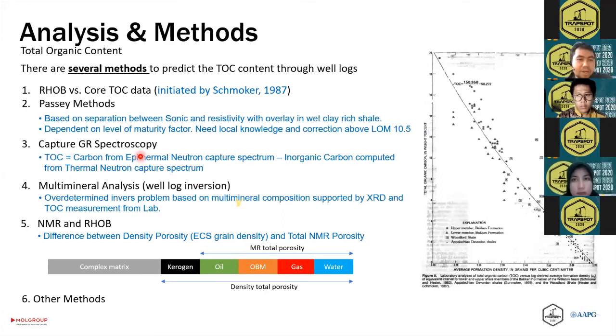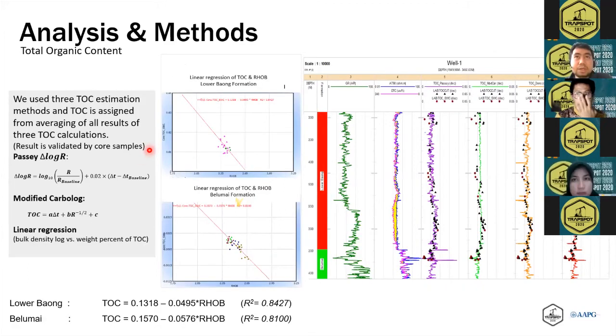What I did to calculate the TOC, you can see here: I have the TOC calculated from the Passey method based on delta log R. I have the modified Carbolog method from multilinear regression, and the other one is linear regression from the Schmoker method, which is a very simple way. This is the density versus the TOC that I calculated at that time, and you can see the distribution of the density TOC, shown by the orange line. It's quite a good TOC compared with the core and the cuttings data.